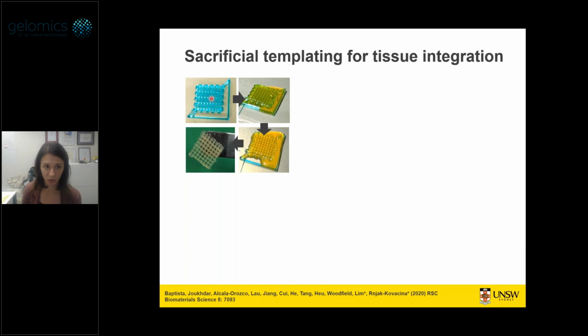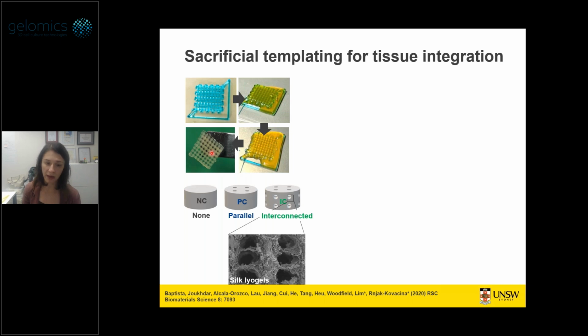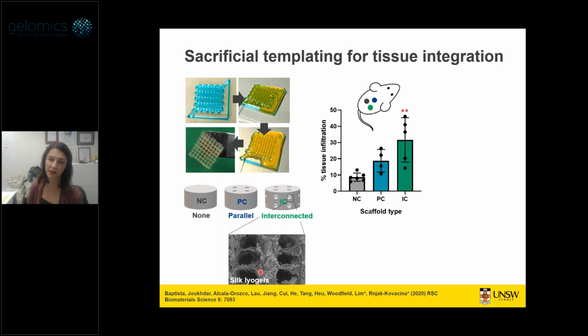And so we use the same approach: print out Pluronic, cast silk, cross-link, get rid of Pluronic, to make three types of materials out of silk. We made materials with no channels. We made some materials with just parallel vertical channels that are about 500 micrometers in diameter, running in one direction, and then some channels that were interconnected, running in both directions. And then we lyophilized these to give them porosity in the bulk as well, not just through these channels. And then we implanted these in vivo, subcutaneously in mice, and looked at the percent tissue infiltration into these.